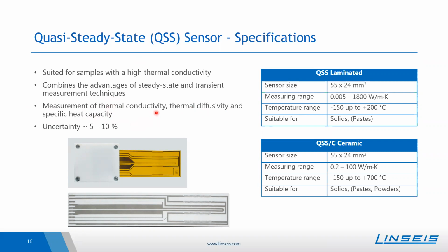It has a slightly lower uncertainty because here the calibration is also more crucial. So all of the sensors need to be calibrated with a suited reference material. And as you see here, we have a very, very broad thermal conductivity range, and one needs to take care which calibration reference material one uses to have the highest possible accuracy of measurement.